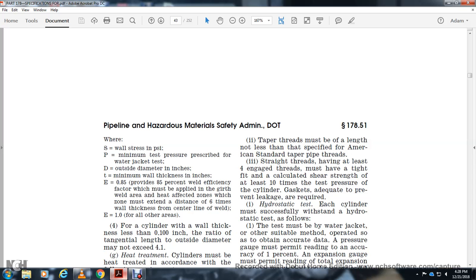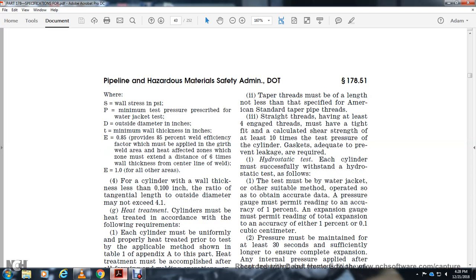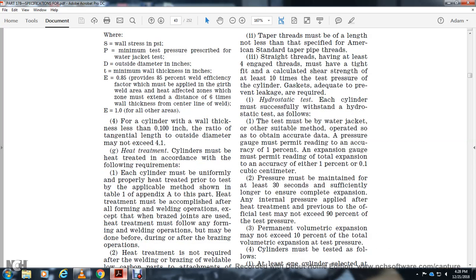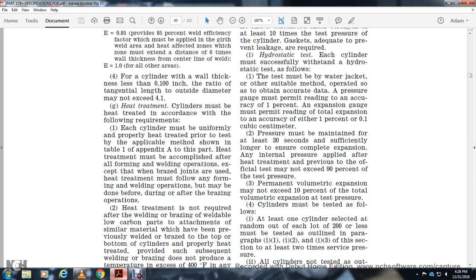Required hydrostatic test: each cylinder must successfully withstand a hydrostatic test as follows. This may be done in a water jacket or by another suitable method of operation, obtained with an accurate pressure gauge. The gauge must permit reading of the pressure accurate to within 1%, and the expansion gauge must permit reading of the total expansion with an accuracy of 1%, or 1/10 of a cubic centimeter. Pressure must be maintained for at least 30 seconds, or sufficiently longer to ensure complete expansion. The internal pressure applied after the heat treatment may not exceed 90% of the test pressure. Permanent volumetric expansion may not exceed 10% of the total volumetric expansion.